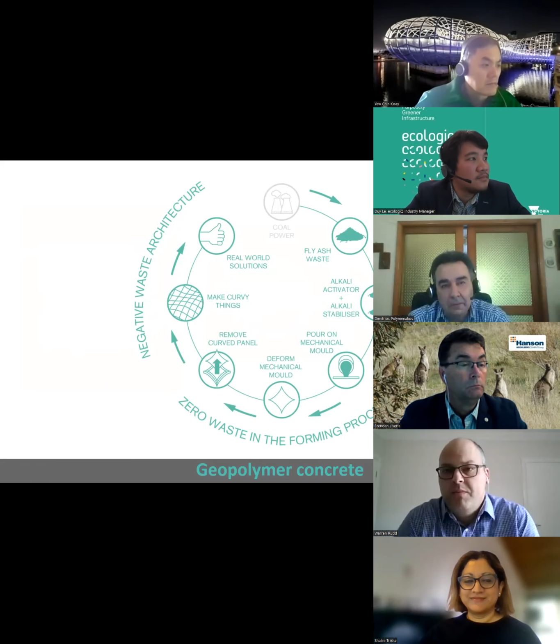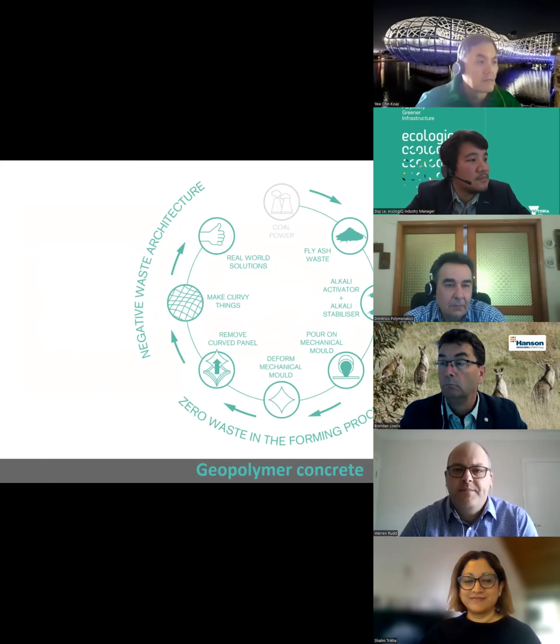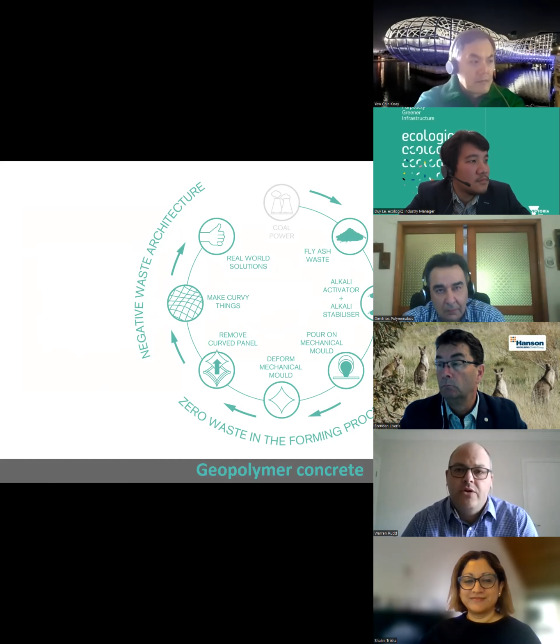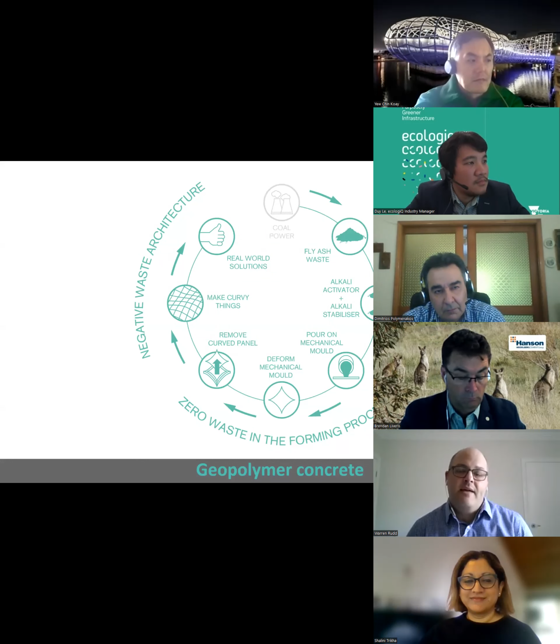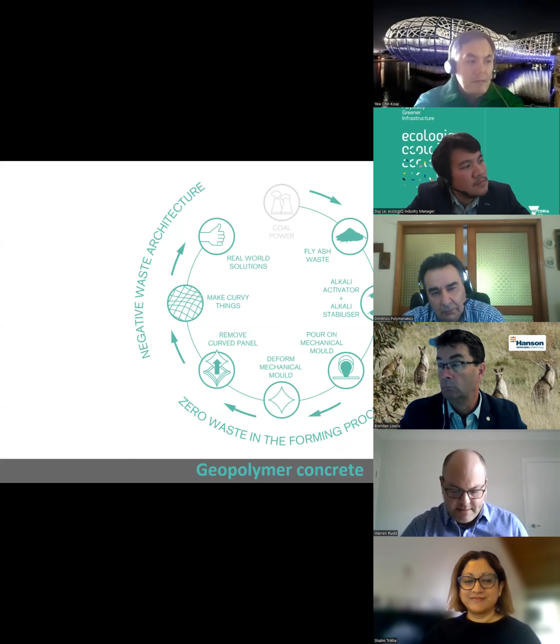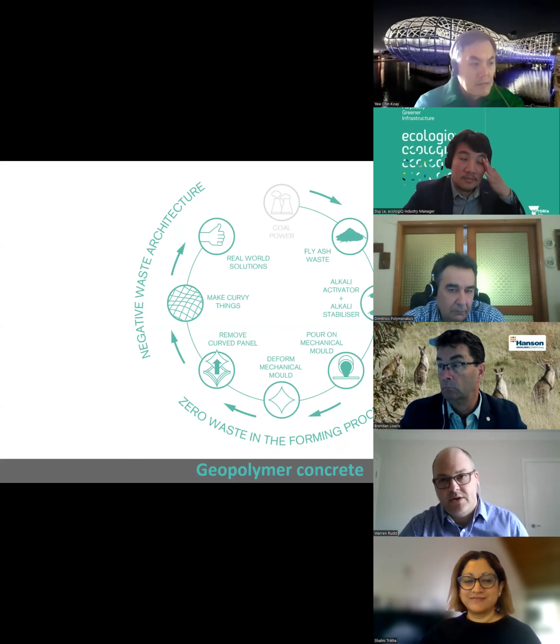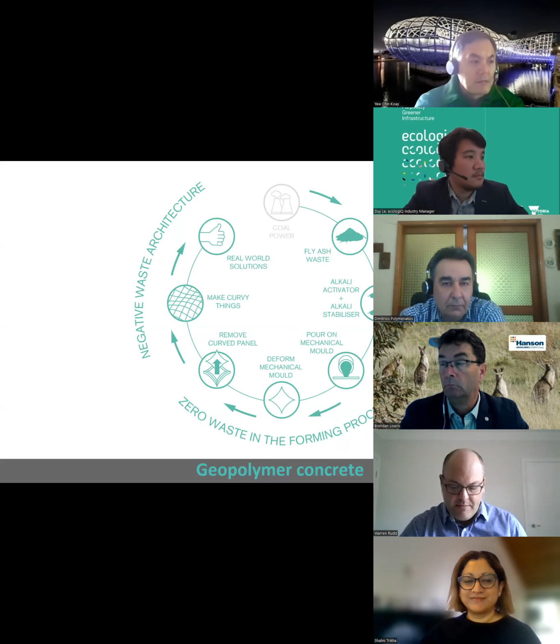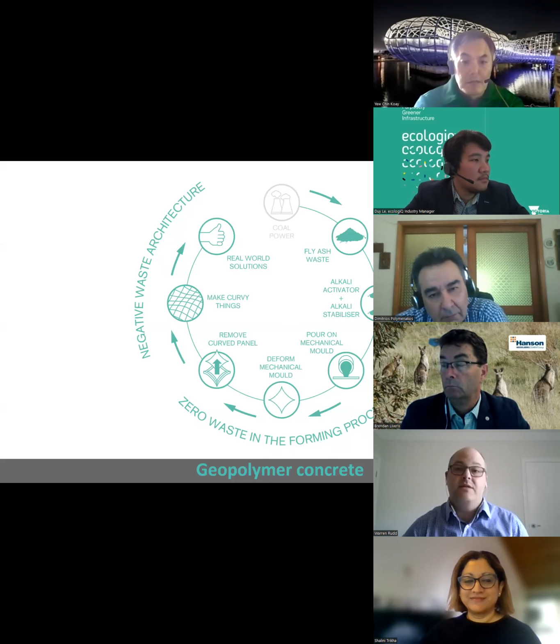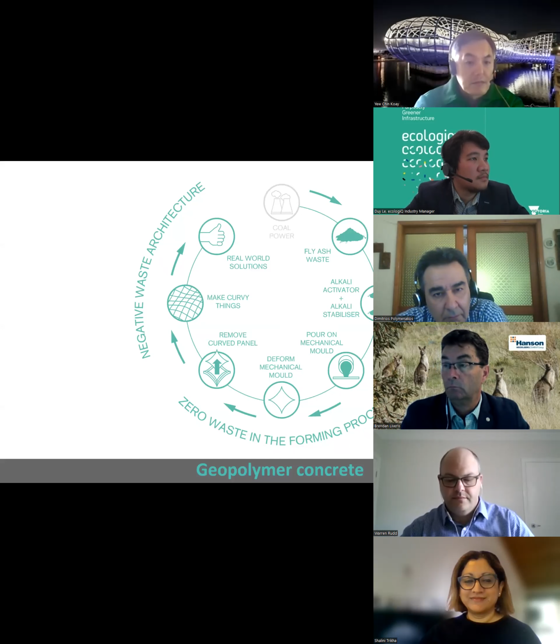We use a geopolymer. We've created our panels using a geopolymer. We have developed it in-house. We do not use any Portland cement in our mix. It's fly ash and slag, and then we use an alkali activator. And that really gives us properties that are pretty similar to traditional Portland cement for the applications that we're looking at. But the real benefit is it's up to an 80% reduction in CO2, and it has a positive waste footprint.